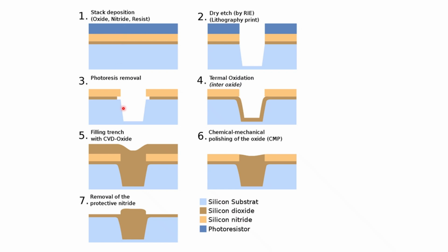And one can combine such DRIE process. It's not just useful for MEMS, but it's also useful for IC. For example, you can use a DRIE process to etch trenches in silicon with very narrow defined geometries, grow thermal oxide, and then grow CVD oxide, use CMP to pattern the oxide and then remove the protective nitride. Now, how to etch the nitride away without attacking the oxide? That's not an easy process. I'm not going to discuss all the details here, but I hope that this illustrates the connection between MEMS and IC in the sense that a lot of tools that were originally developed for MEMS actually found much, much wider use in integrated circuits.